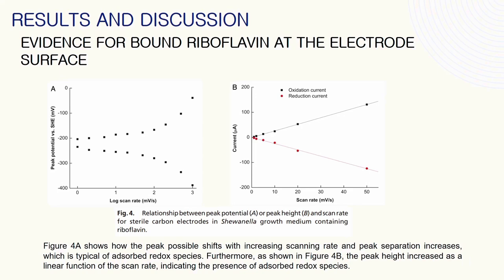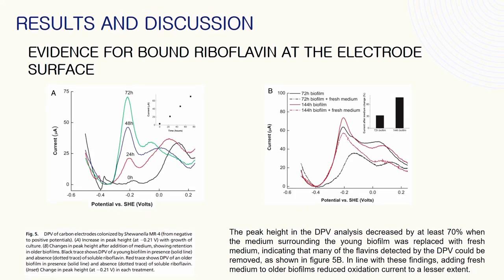Based on the peak height in the cyclic voltammetry data, the amount of riboflavin adsorbed onto the electrode was estimated at 0.2 nanomoles per square centimeter, indicating that as much as 8% of riboflavin in the reactor could be adsorbed. Results and discussion: evidence for bound riboflavin at the electrode surface, using Shewanella colonized electrodes.